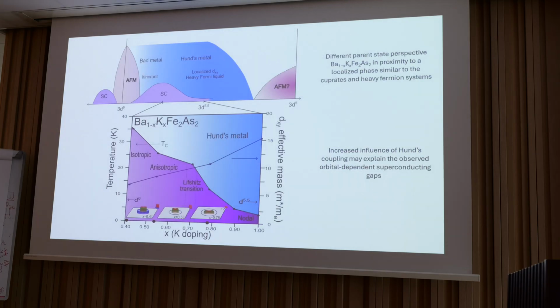from that. So that leads to this picture I have, where you have this different parent state perspective, and in that case superconductivity is emerging from this localized phase, which is much more similar to cuprates as you dope away. Maybe these very localized DXY electrons are acting as kind of the background of the itinerant carriers of the XZ/YZ orbitals.